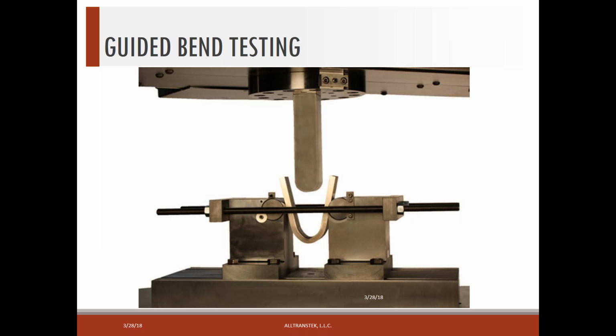Okay, and also another requirement mostly for groove weld procedures is guided bend tests, and most of the time 4 side bends are required, or 2 face bends or 2 root bends are required on thinner material. As an example, if I'm going to weld a 1/4 inch thick material, I probably would not cut a side bend specimen from that for procedure qualification. I would bend the face of the weld and the root of the weld instead. 2 face bends, 2 root bends instead of 4 side bends.